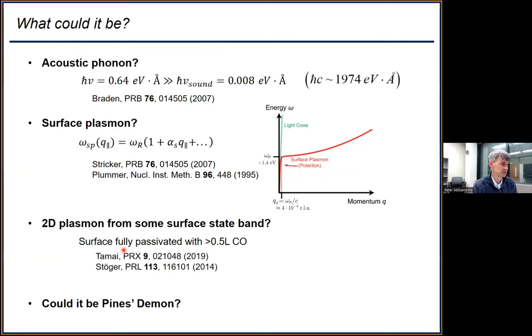At first I assumed it was an acoustic phonon, but if you look closely, it's not an acoustic phonon. The reason is it's about a factor of 100 too fast. Acoustic phonons travel at the sound velocity. The sound velocity in strontium ruthenate in suitable units is about 10 to the minus 2 eV angstrom. The velocity of this mode is about 0.64, so it's about a factor of 100 faster than the sound velocity. This velocity is actually of order the Fermi velocity, so it's way too fast. It's really something electronic. It's significantly slower than a photon, by the way. H bar C is 2000 eV angstrom, so it isn't some polariton mode or something like that. It's something that's got the same speed as the Fermi velocity.